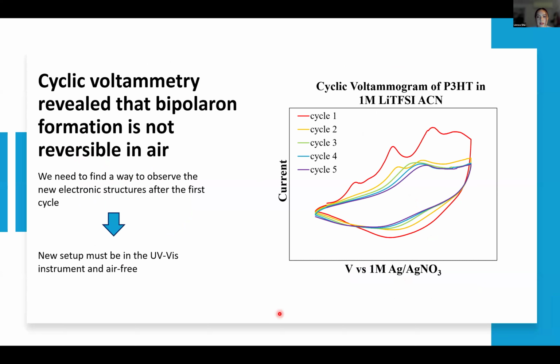So here is a sample CV that we took in air. And as you can see, after the first cycle, we get a lot of peak loss, which we don't see when we cycle under argon.